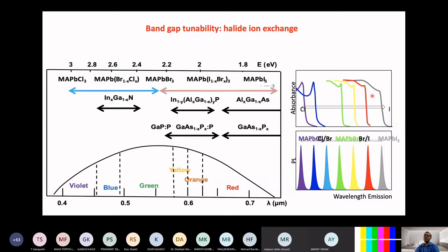So certainly from this particular graph data, it suggests that the gray portion is useful for solar cell application. However, these very nice, very narrow emission spectra, these are actual emission spectra, not schematic, these are all experimental data. So you see the very narrow emission coming from this perovskite, which is clearly a signature of the very good crystalline quality of these materials. And it can be tuned all the way from red, yellow, like you are making all your VIBGYOR.